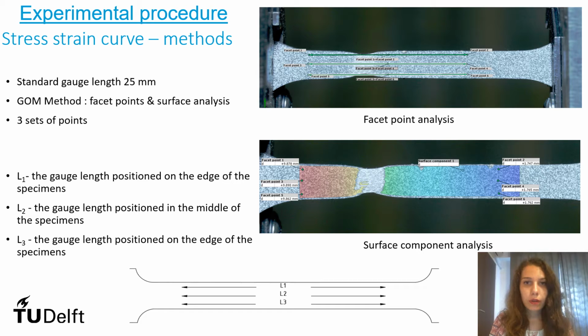Regarding the stress-strain curves methods, the standard gauge length of 25 mm was used, and in GOM, I used two types of analysis, which are the facet point and the surface analysis. For both analyses, I defined 3 sets of points and the gauge length between them. 2 gauge lengths were on the edges of the specimen and 1 in the middle. Both types of analysis, the surface and the facet point analysis, provided similar results.